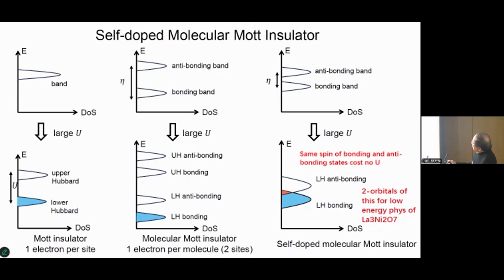Then if I consider the molecular case, I have anti-bonding and bonding states already. Each bonding and anti-bonding state, because of U, can have an upper Hubbard band and a lower Hubbard band. So what I draw here is a lower Hubbard band for bonding, a lower Hubbard band for anti-bonding, and the upper Hubbard bands for bonding and anti-bonding, so 4 states because of the Coulomb. That is the molecular Mott insulator, with doping 1/4. This is doping 1/2.